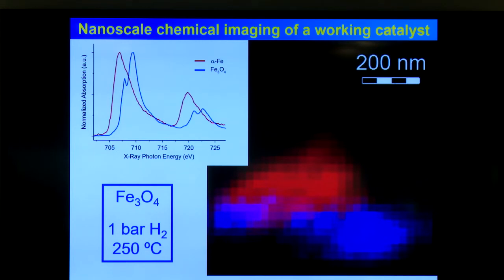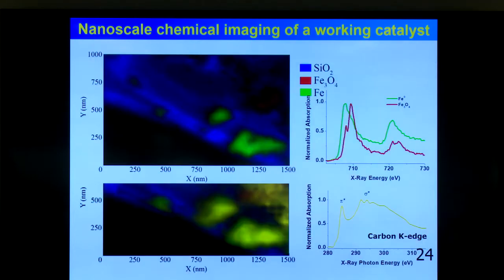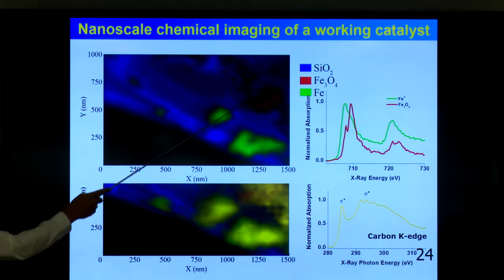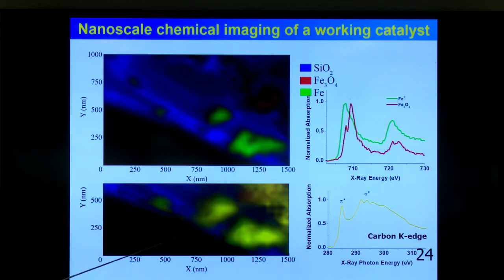Okay, you don't stop there, of course. You completely reduce the nanoparticle, and then on a real Fischer-Tropsch catalyst. Actually, this was a very bad catalyst. Some of the particles were iron. This is in green now. Some were not reduced, so they are still oxidic. But that actually gives us an ideal system to do Fischer-Tropsch and then switch to the carbon K edge and look at the nature of carbon at the oxide and at the metal particle. This one is supposed to do Fischer-Tropsch, and this is an oxide particle, which is probably used to doing something else. So by studying the nature of the carbon spectra, we could correlate the reactions happening on different nanoparticles.